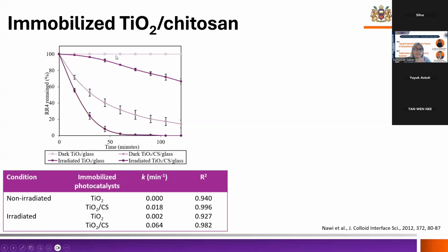So this first line here is the TiO2 only adsorption. There's no adsorption properties by the titanium dioxide for Reactive Red 4. And then this is the TiO2 under irradiation, which is in the presence of light. So you can see little improvement in the titanium dioxide only. And then when we combine titanium dioxide with chitosan, you can see a significant increase in the adsorption performance of the photocatalyst. And the removal under photocatalysis is even better.